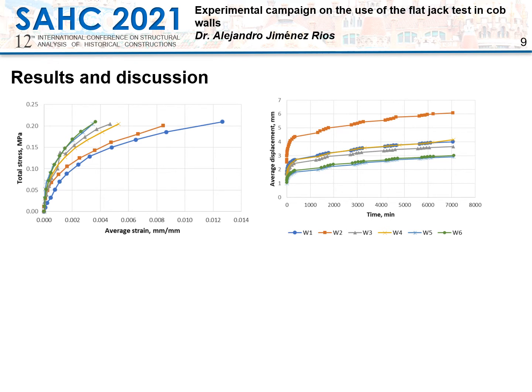The full consolidation of a soil is only achieved after a relatively long period of time, hundreds or thousands of years even. For practical reasons, though, it was accepted that for this experimental campaign, the level of consolidation will be such that further deformations caused during the time period of the performance of the flat jack test will be negligible. For example, when the displacement increment due to the cob consolidation were less than 1%. To achieve this, the load used for consolidation, roughly 85 kilonewtons, will be bigger than the load at which flat jack test will be performed, approximately 50 kilonewtons.